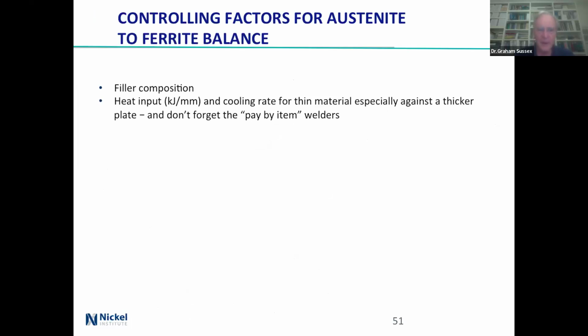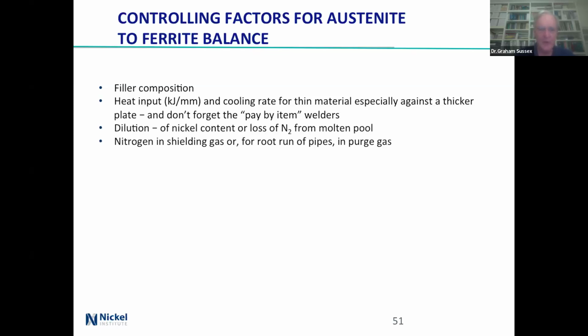Okay, now we're looking at ferrite balances. Filler composition, what heat input is there, and the cooling rate for thin materials, especially if you're going against a thicker plate. And don't forget about people who are trying to get through very quickly and putting lots of heat in, because they're paid per the item. Dilution, the nickel content, loss of nitrogen from the weld pool. I've just shown you the example of that.